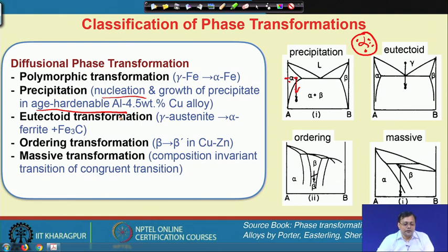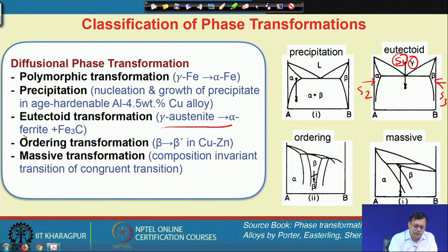The third type of diffusional phase transformation is the eutectoid transformation. In a eutectoid transformation, it is a solid transformation, meaning we start from a solid phase, solid 1, where we will get basically two different solids, S2 and S3 from S1. So, here it is gamma to alpha and beta. This is just a schematic we have shown, and a specific example of such transformation is the gamma austenite that transforms into alpha ferrite and cementite. Cementite is a metastable phase also, and the eutectoid transformation we all know. So, here let us say alpha and beta will evolve from gamma.